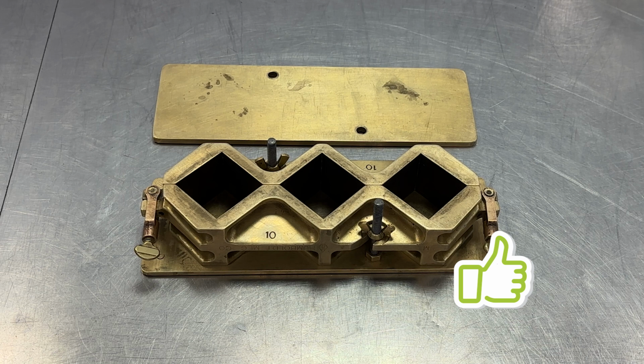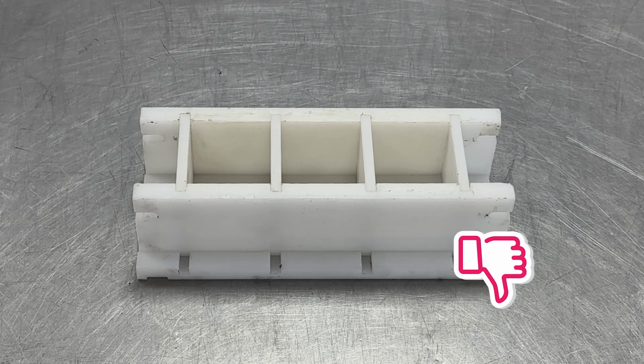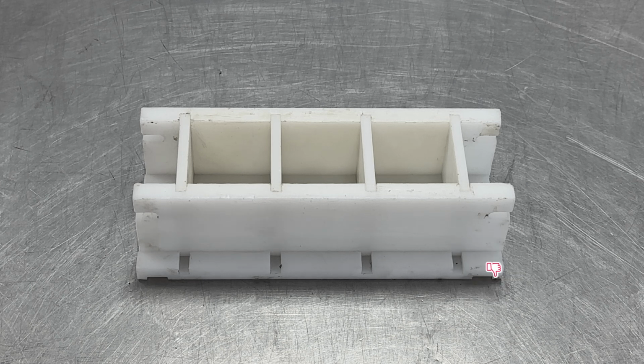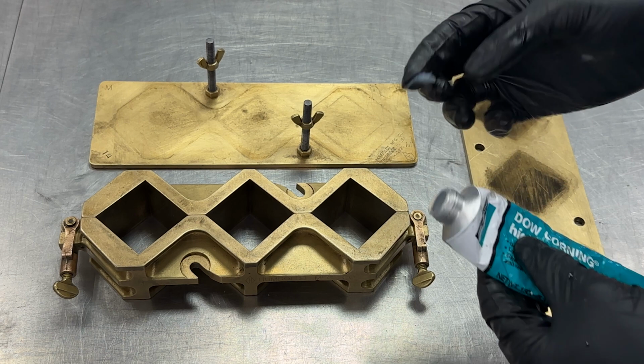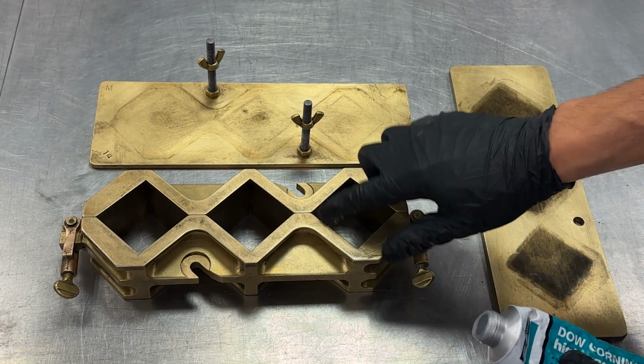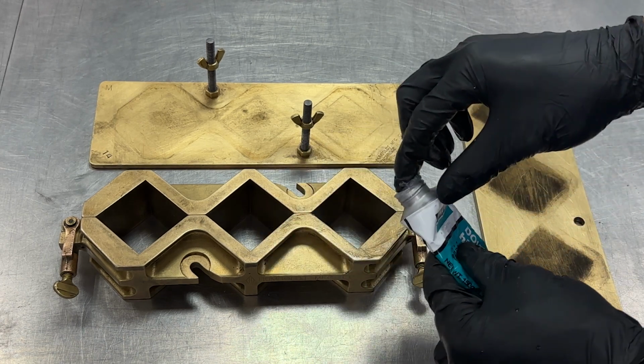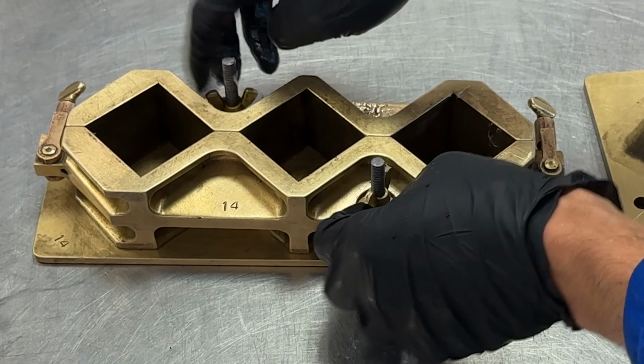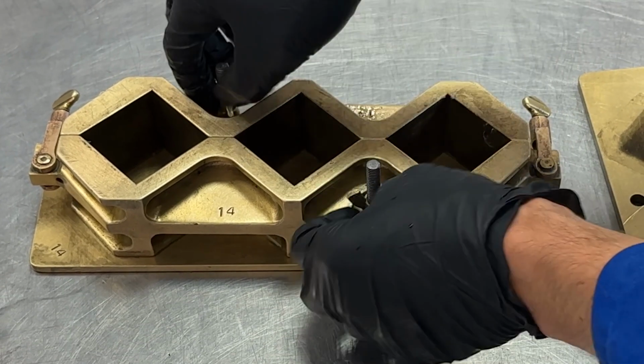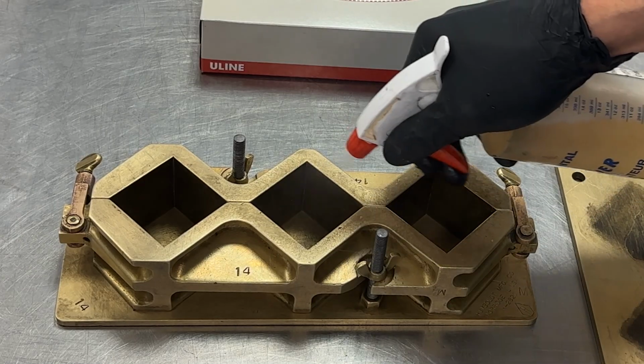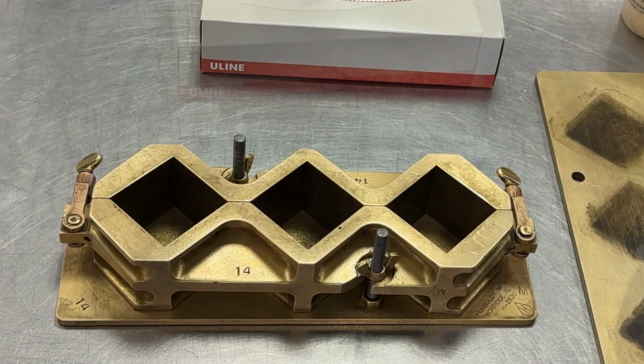For the sample fabrication, only the metal mold is acceptable as shown here. Plastic molds are not acceptable as they will deform due to the exothermic reaction of the cementitious product. If the sides of the cubes aren't parallel, it could cause a shear failure instead of a compressive failure. The mold should be made watertight with wax or silicone. Spray an oil on the inside of the mold and wipe off any excess.